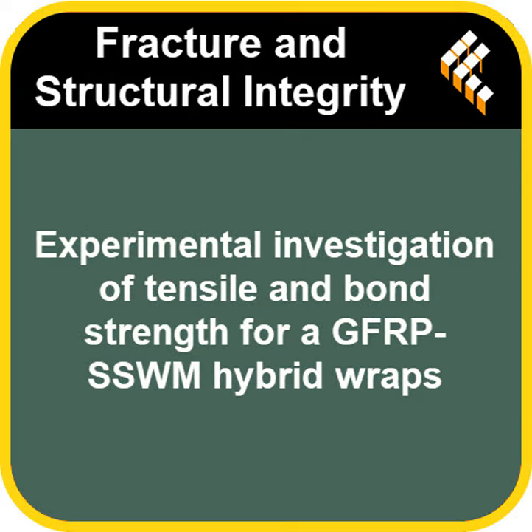Why? What's the difference between them? It comes down to material properties, revealed by looking closely at the failed surfaces, what they call fractographic analysis. Like forensic science for materials. Kind of, yeah. Sikadur 30 LP has a lower viscosity. It's runnier. Okay. Which means it could penetrate deeper into the stainless steel wire mesh, creating a stronger mechanical interlock, a better bond. Ah, so it really got in there. Exactly. Sikadur 330, on the other hand, seemed to bond better with just GFRP. But when the SSWM was involved, the bond wasn't as strong. It struggled to wet the steel mesh as effectively.